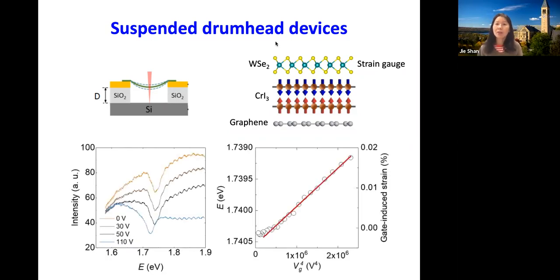It has a very strong interaction with light, and the optical response of this is typically a very strong exciton resonance. So this is taken from this device. If you look at absorption, this large dip corresponds to the fundamental exciton in this material. If you apply gate, apply strain, you see a systematic shift of the exciton resonance. And this is in a relatively small range of strain. The exciton resonance shift scales linearly with strain. We can pre-calibrate this, and this serves as a strain gauge. So we can independently measure the strain level, assuming the 2 layers do not slip.